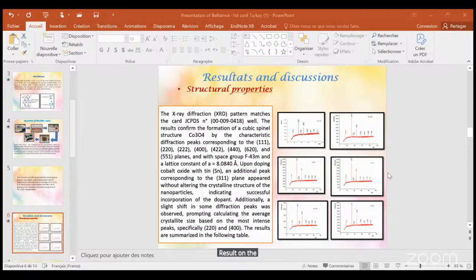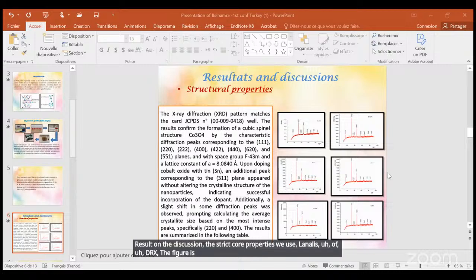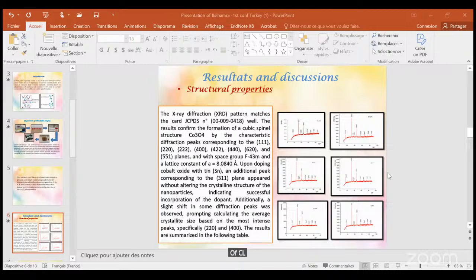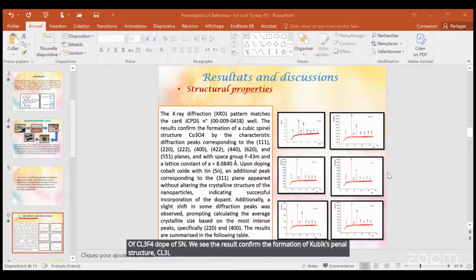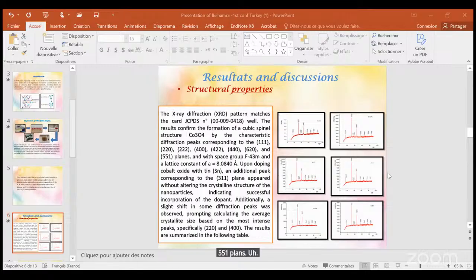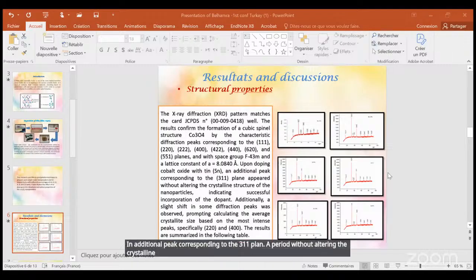Results and discussion. For the structural properties we used XRD analysis. The figure shows the XRD pattern of Sn-doped Co3O4. The results confirm the formation of a cubic spinel structure of Co3O4 by the characteristic diffraction peaks corresponding to the 111, 220, 222, 400, 422, 440, 620 and 551 planes. With Sn doping of cobalt oxide, an additional peak corresponding to the 311 plane appeared without altering the crystalline structure of the nanoparticles, indicating the incorporation of the dopant.